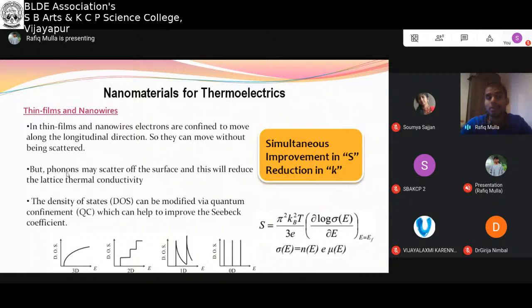But in case of phonons, they are not confined exactly like how electrons are confined. So phonons may scatter off the surface, and this will reduce the thermal conductivity. So phonons can be scattered off from the surface of the nanowires because of the very narrow thickness of the nanowires, as well as the very small thickness of the thin films. From the surface itself, a significant amount of phonons can be scattered. So once phonons are scattered more, then there is a significant reduction in the thermal conductivity. Particularly, it is lattice thermal conductivity.